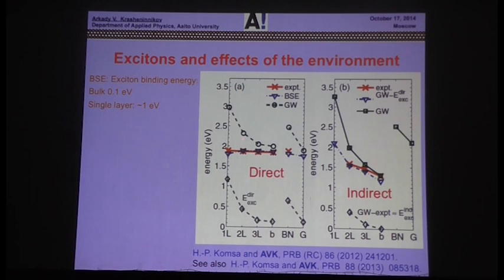And then, if you look at the experiment, these brownish points here, and results of calculations. So once more, you first do standard DFT, on top of that you do GW calculations, with spin-orbit coupling, and on top of this you solve the Bethe-Salpeter equation. You get a very nice agreement with the experiment here, basically these blue and yellow points. You can also account for the effects of environment, like boron nitride on graphene.